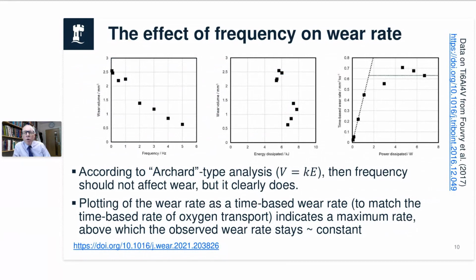I'm just going to very quickly touch also on some work on frequency, because again, with frequency, Archard shouldn't really make any difference. If we adopt an Archard approach, the one that says the volume is proportional to the energy, then the frequency shouldn't make any difference. But there was work that was published by Fouvry et al. in 2017, on the left-hand figure there, where they said that the wear volume under a certain set of conditions really fell off very, very quickly as they increased the frequency from about 0.5 hertz up to 5 hertz.